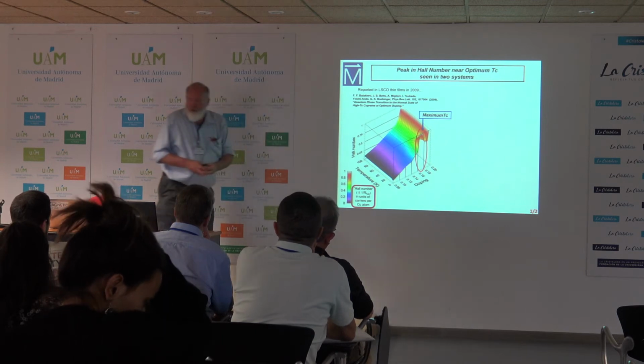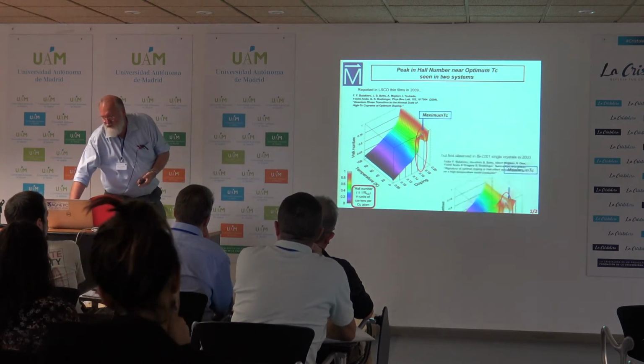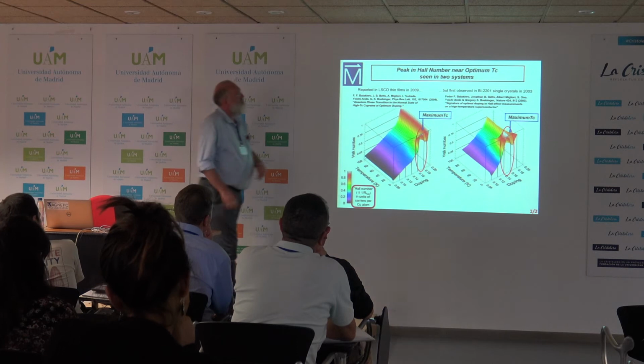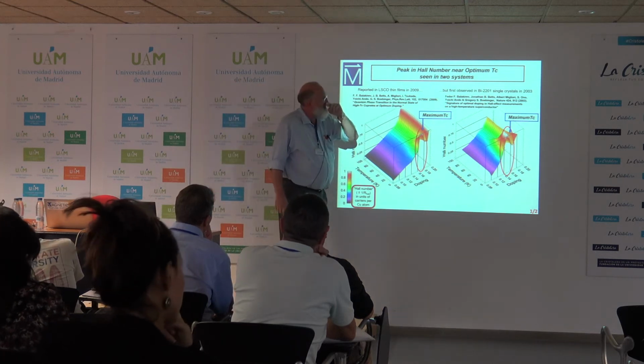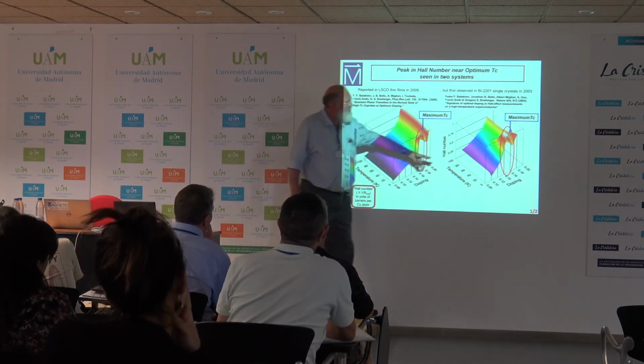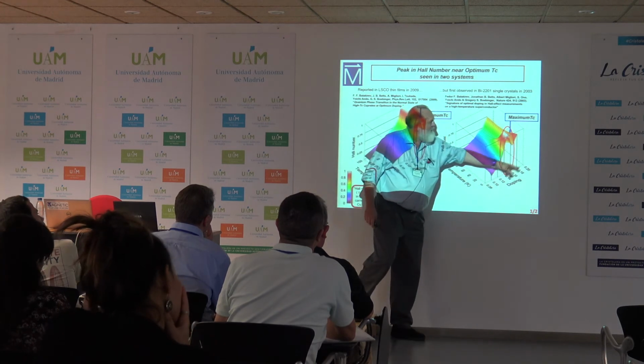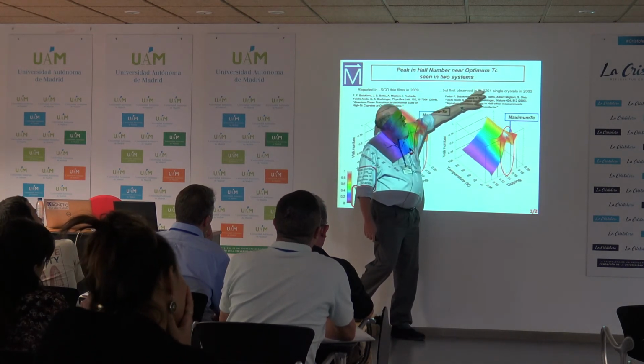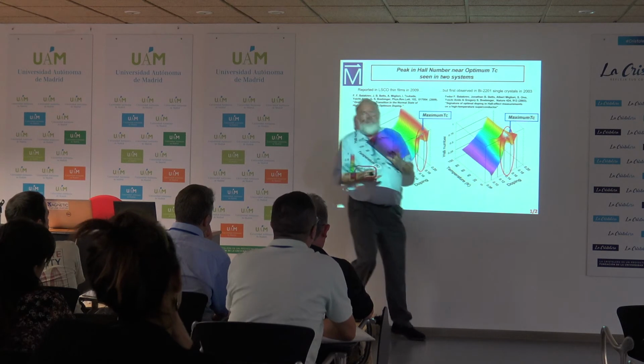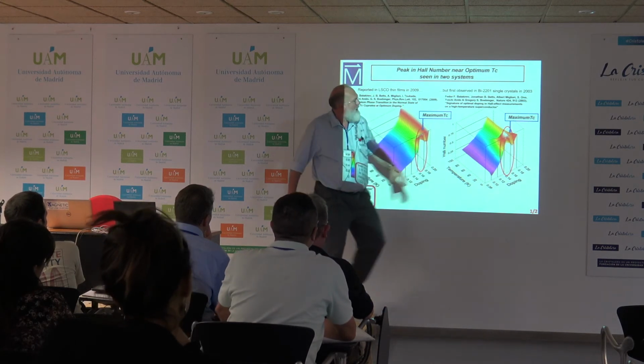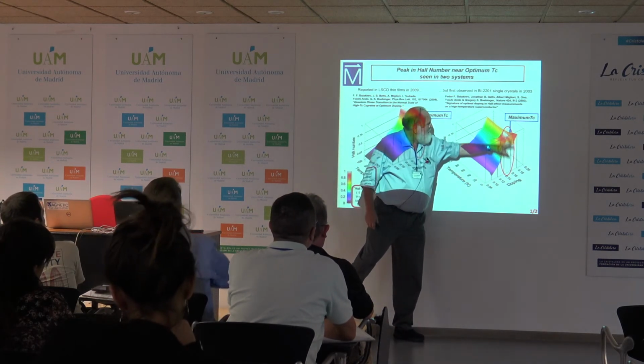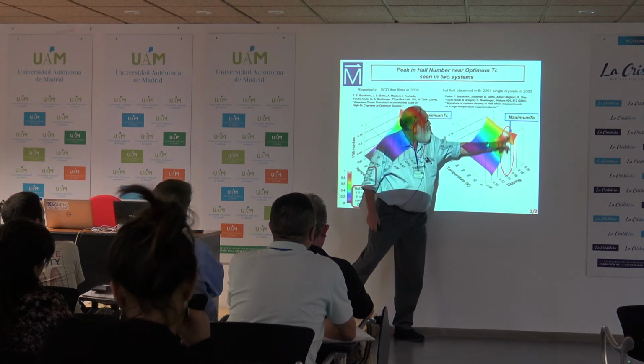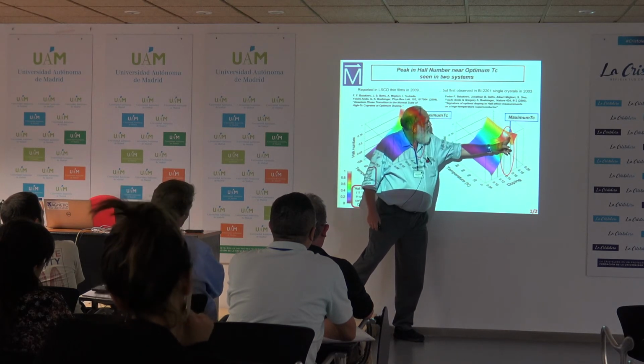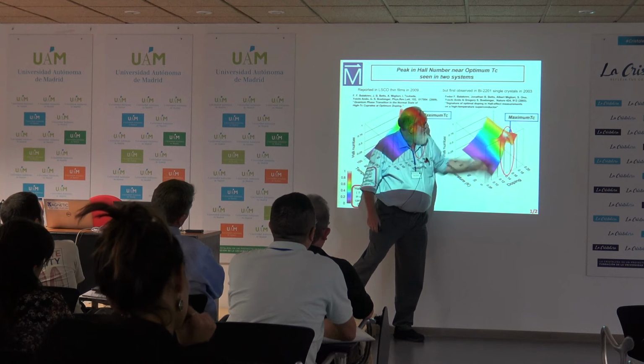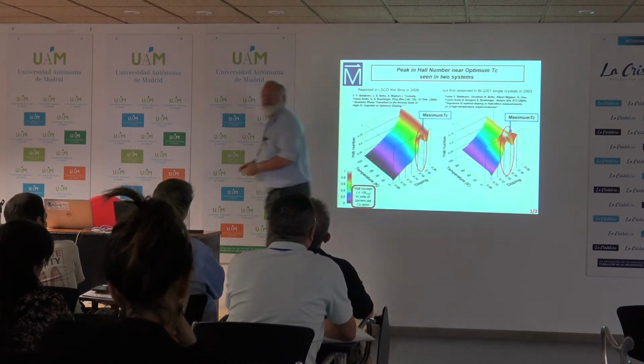These are results from 2009. We actually first saw this effect in BSCCO, because it comes in platelet-like samples, in 2003. Here it's much harder to know the exact doping, because as you're pumping lanthanum in, you're clearly getting oxygen compensating, so you don't really know your doping. But the point here is that even if this is not the precise number, the maximum TC is once again just near this peak in the measured Hall number.